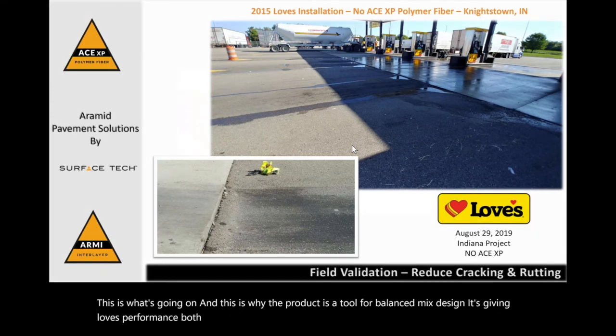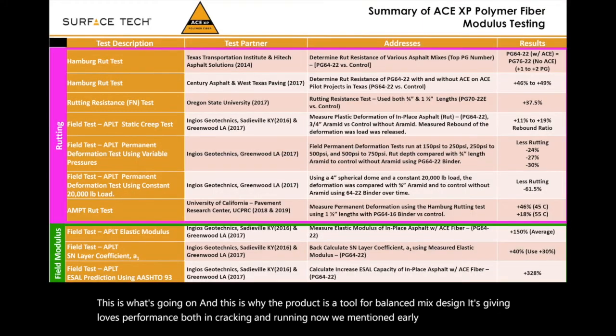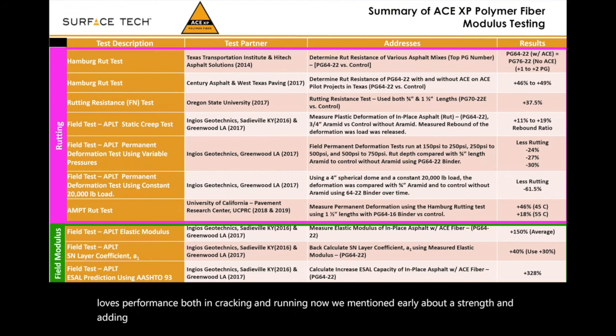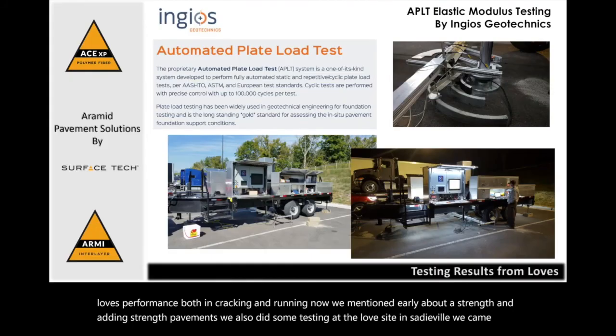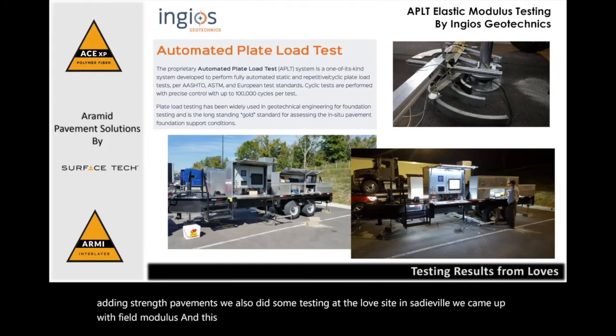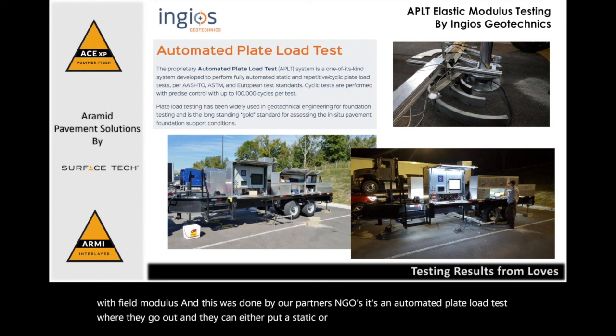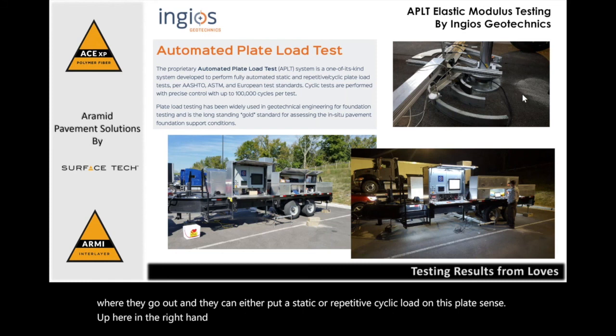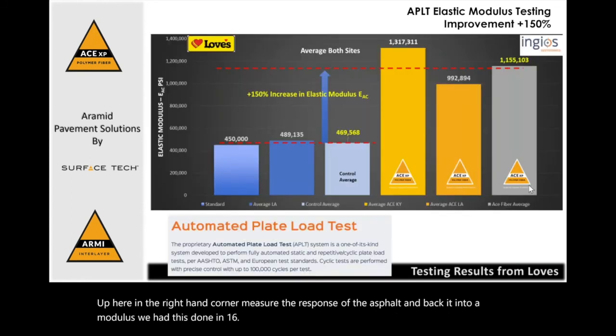Now, we mentioned early about adding strength to pavements. We also did some testing at the Love's site in Sadieville, and we came up with field modulus. This was done by our partners, Ingios Geotechnics. It's an automated plate load test where they go out and they can put either a static or a repetitive cyclic load on this plate sensor up here in the right-hand corner, measure the response of the asphalt, and back it into a modulus. We had this done in 16. And the results were staggering.